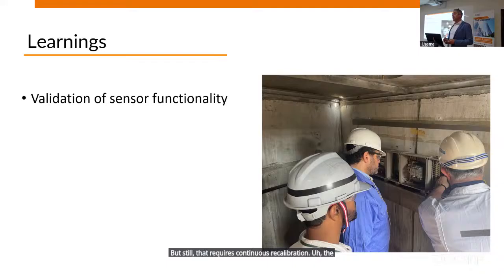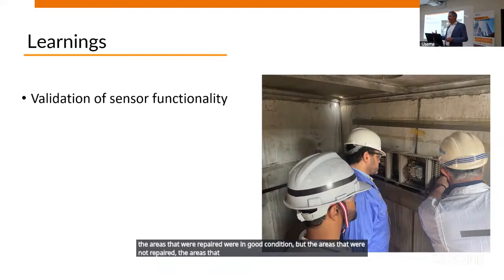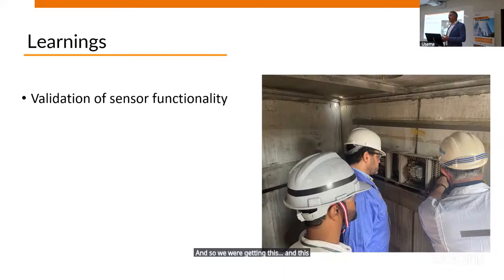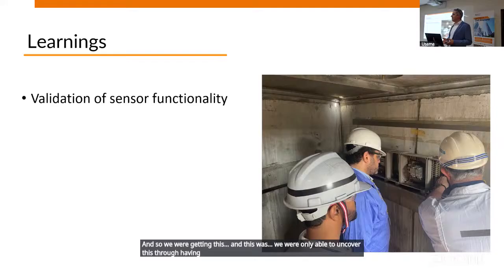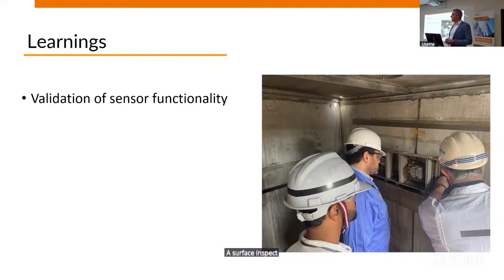The coupons provided us with the biggest insight. And the coupons were able to identify a specific type of corrosion, macro cell corrosion, that is occurring, where the repaired areas were protected. The areas that were repaired were in good condition, but the areas that were not repaired, the areas that are in anaerobic environment, were acting as the anode to the repaired areas. And we were only able to uncover this through having a monitoring system. A surface inspection wouldn't have uncovered this.